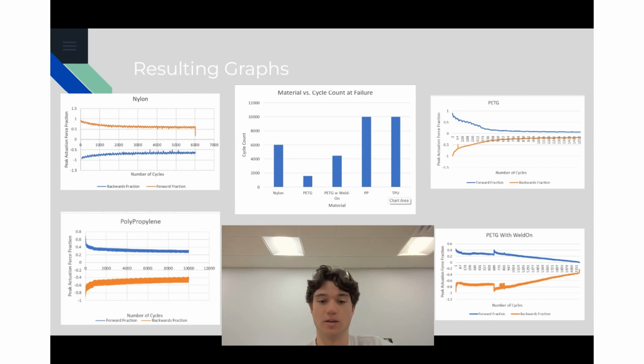The TPU and the polypropylene ended up doing very well over the full 10,000 cycles. And the PET-G ended up snapping about 1,500 cycles in. And the PET-G with Weld-On made it a little longer, but didn't last the whole 10,000 either. And the nylon lasted about 6,000 cycles.